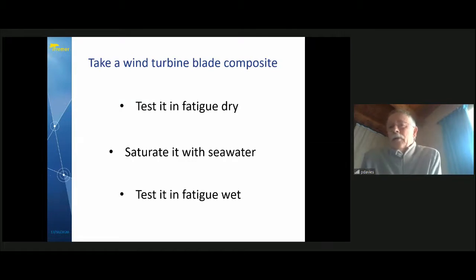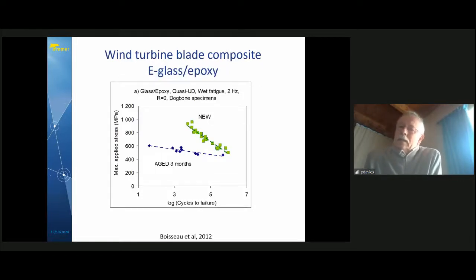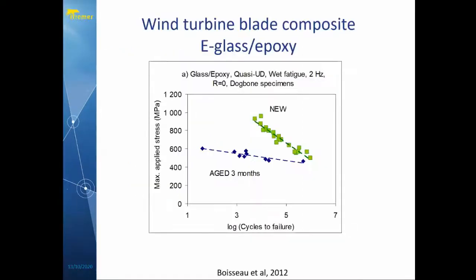So the idea we had was to take a wind turbine blade composite, test it in fatigue dry, then saturate it with seawater and test it again wet. Next slide. And this is the kind of result which we got. So we have the curves, the green, where we have the new material, which was fatigued. We do all our tests in seawater also, but over the test time, the water didn't have time to saturate or get very far in this particular composite, which is a glass epoxy. And then we did the same thing after aging for 3 months, which was the time it needed to get fully saturated, in this case, raising the temperature. And you can see a very big difference between the two curves.